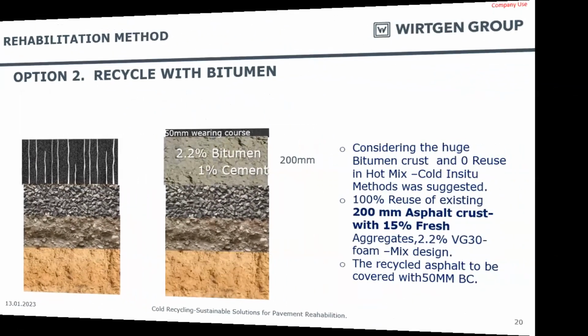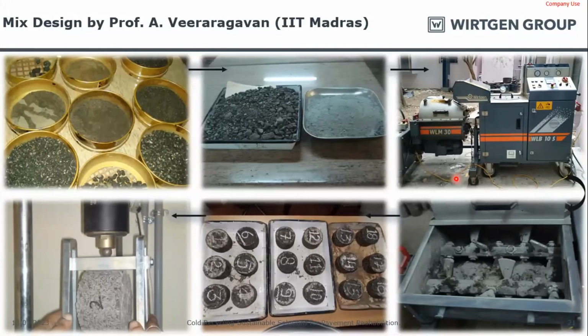So this was a mix design that we did at IIT Madras under the guidance of Professor A. Veera Raghavan. Here the samples were collected, we checked the gradation and we put them inside a pavement. So this is a Wirtgen foam lab. We check it to find the optimum foam water content as well as temperature to find the optimum foam design. The optimum foaming process is tested to find the optimum percentage of water as well as temperature, to gain the maximum expansion ratio as well as half-life.